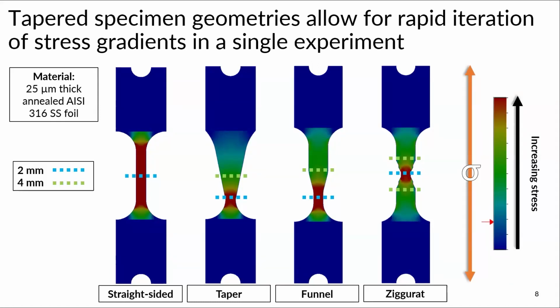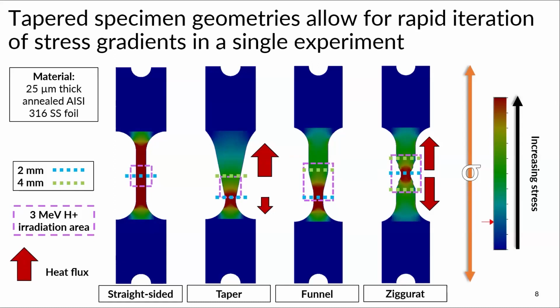The reason we did that is because in the first two experiments, we had a significantly smaller irradiation area. And we realized with the taper specimen, the heat flux and the heat flow throughout were quite uneven. On the first tapered experiment, we ended up having a temperature spread of about 150 degrees C, and that's hard to deal with because you're really only supposed to be changing one variable. So we're hoping that with the ziggurat's geometry, it will have an even heat flux through the center and then up and out both of those directions.